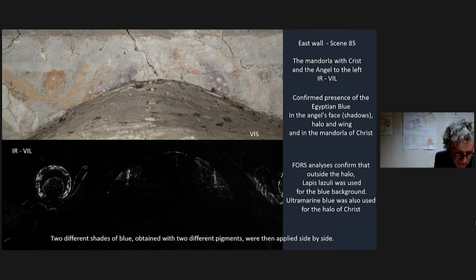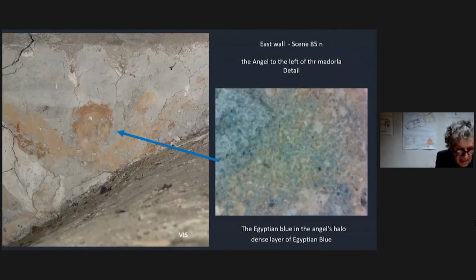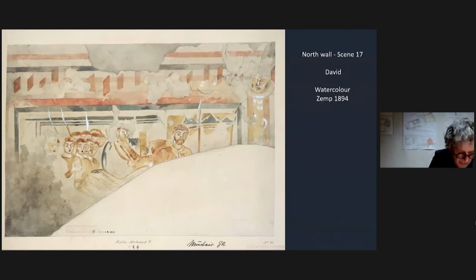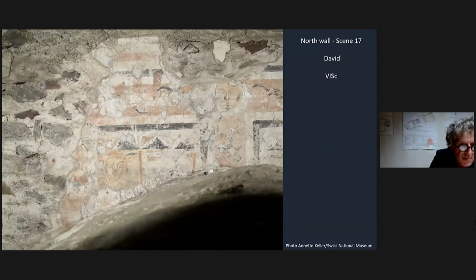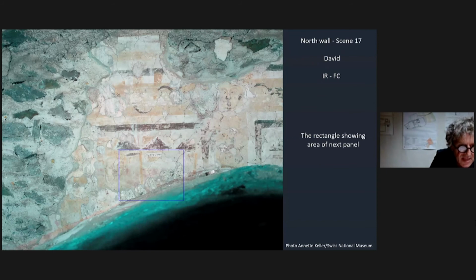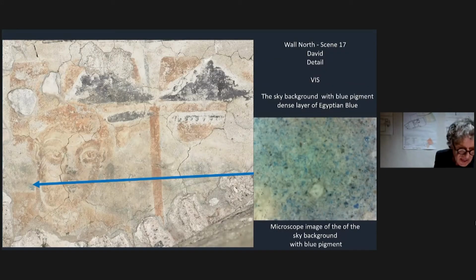Lapis lazuli was used for the blue background and also for the halo of Christ. The Egyptian blue is in the face shadow, halo and wing of the angel in the mandorla behind Christ. In the angel's halo, there is a dense layer of Egyptian blue. Extensive use of this pigment is documented in other frescoes. You can see in the images the sky background with blue pigment showing a dense layer of Egyptian blue, confirmed by a thin section of a sample.